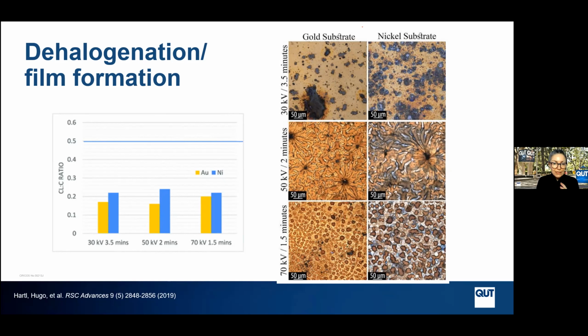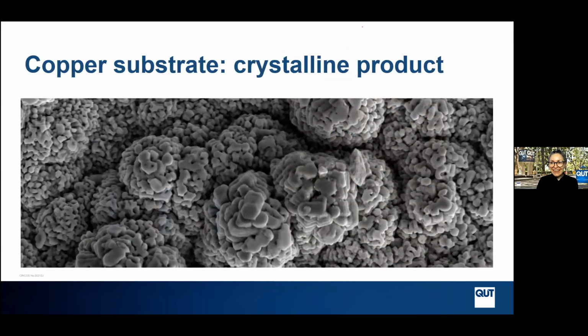And what's shown to you here in the XPS data, which don't actually look like XPS data, this is just the quantification showing you that our chlorine to carbon ratio drops significantly through this process. And we interpret this, of course, as a dehalogenation reaction where the plasma has assisted dehalogenation of these molecules at the reactive metal surfaces. We cannot reproduce this result without a metal substrate, which is why we think it's plasma-assisted dehalogenation. Interestingly, though, we started to expand the work to look at molecules that had some different halogens on them and to look at a different substrate. We also moved to a different plasma apparatus, so there were a few perturbations here, but Hugo started very repeatedly seeing crystalline products, which we had never observed before.